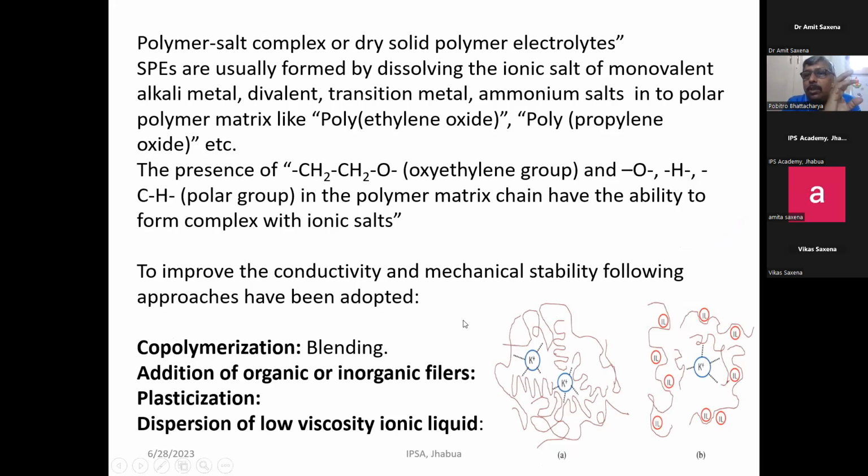The focus shall be towards the enhancement of the conductivity, because ultimately, when we are talking about the use of a polymer electrolyte in a battery or other applications, the conductivity is a very important factor. If the conductivity is not high, the internal resistance of the device will become high, and that may hinder the process, at least the charge migration we are expecting. At the same time, offering high resistance means I squared R, so heat will be generated.